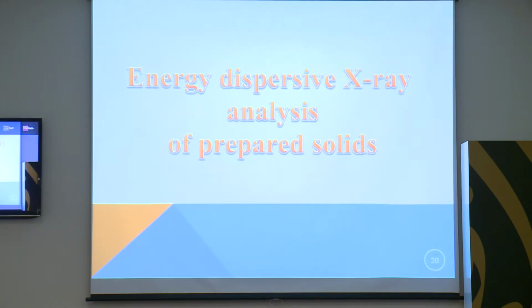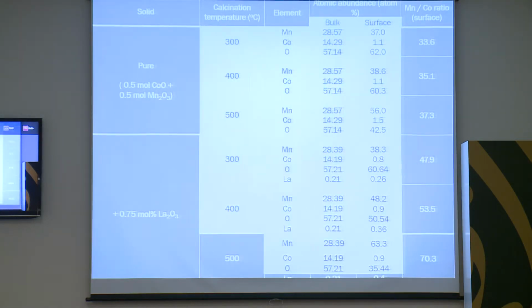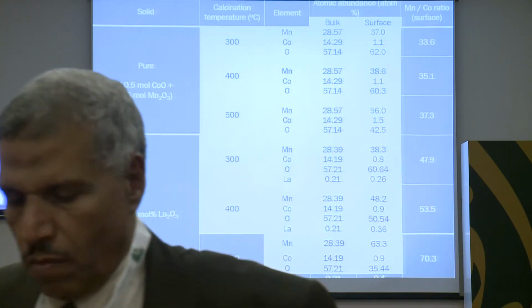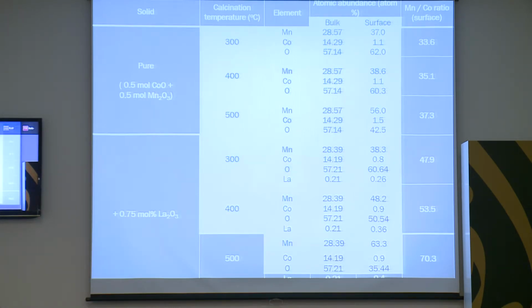In studying the energy dispersive X-ray analysis of our prepared solids, the bulk and surface contents of different ions that exist in these pure and doped solids were listed in this table, and we can conclude from this result that, number one, for all samples, by increasing the calcination temperature, there is an increase in the concentration of manganese species. Number two, for all solids, the percentage of cobalt cation present on the surface was much lower than that in the bulk. This may be due to the precipitation of cobalt hydroxide in the co-precipitation step in the experimental being earlier than manganese hydroxide.